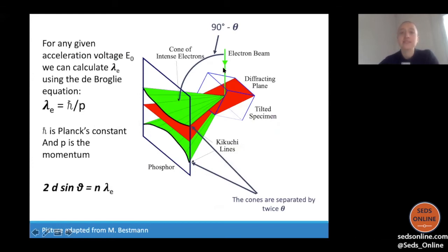What I really want to show here is that when the electron beam gets diffracted, it's diffracted by the crystal lattice of the mineral that we're shooting at. So if you have an amorphous sample, you will not get any diffraction pattern. But if your sample has a crystal lattice, you can resolve the type of lattice, so basically the mineral and the dimensions, and sometimes even the formations in this mineral, using these cones of diffraction that are recorded on the phosphor screen. And these cones actually are, you know, cones. They would form a bent line. But because the phosphor screen is very small, we see them as essentially straight lines. And they are called Kikuchi patterns after the researcher who discovered them.